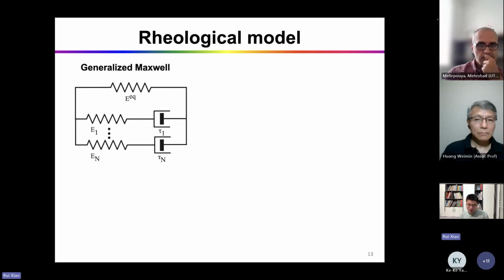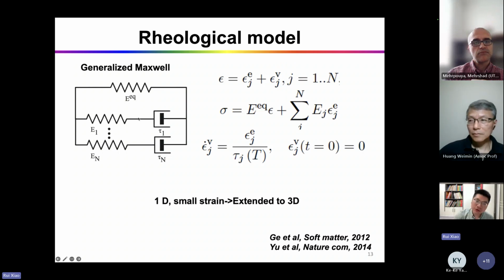You can have this elastic spring that represents the equilibrium state. This actually represents the permanent shape. You also have these processes, a spring-dashpot that represents the relaxation processes accounting for the phase transitions. So what you need to do is make this process, the viscosity or relaxation time, depend on the temperature.